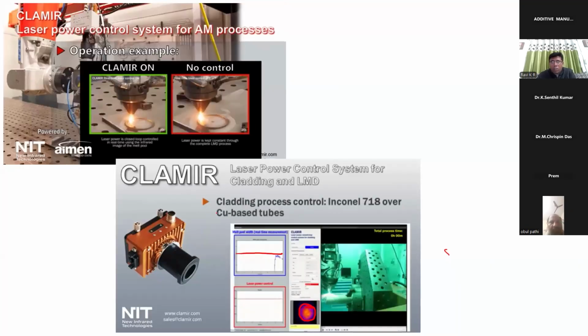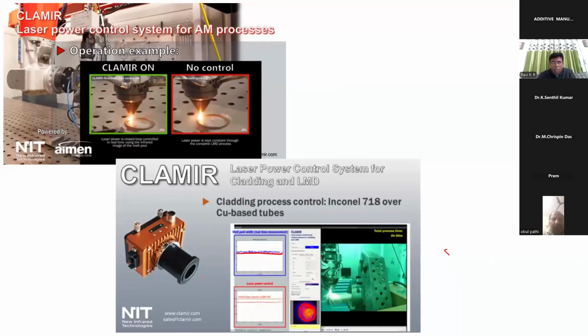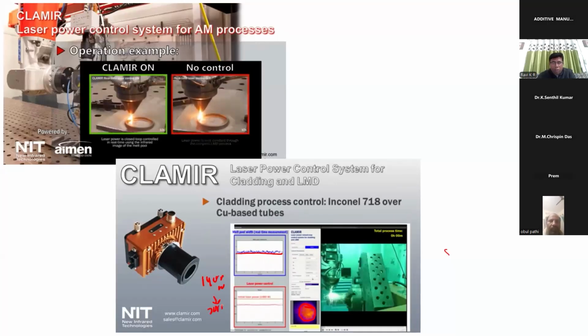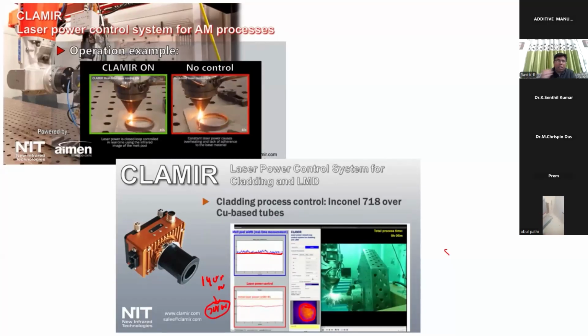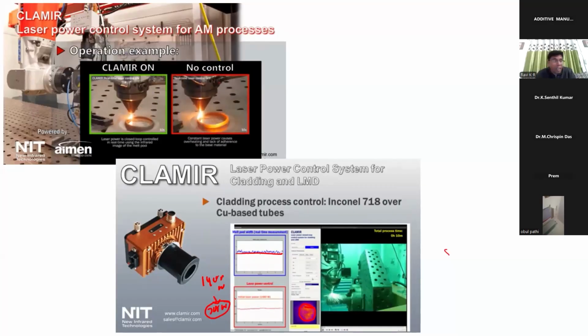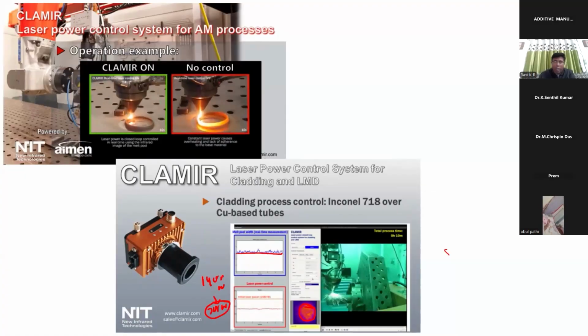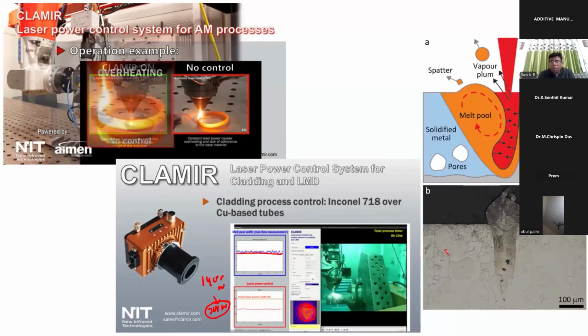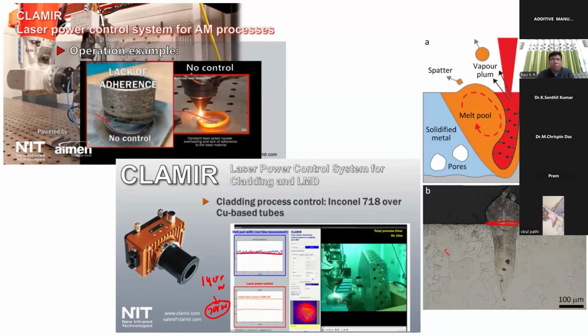So when we start, 1400 is our laser power. Finally, we'll end up with 700 as our laser power. That means I'm continuously changing the power; the power requirement is continuously changing, and I'm trying to decrease it. But this technique will not give you what happens below the surface, because we are putting a camera on the top. So at best you can measure this particular melt pool width.